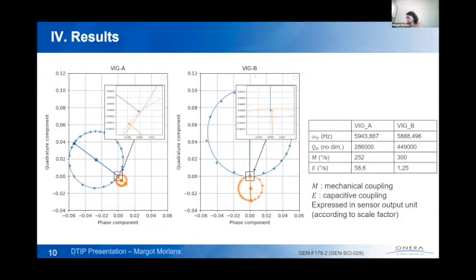We see some capacitive coupling, especially on the sense electrodes, which is particularly problematic since we know that the capacitive coupling has the same phase as the Coriolis coupling, which is, I remind you, our desired output. On the other hand, we see on the VIG B that capacitive coupling is much smaller than on the VIG A. In fact, the VIG B was tuned at factory level, which explains this result. Here in this table, we can see the numeric results. We obtain mechanical and capacitive couplings thanks to a scale factor, so they are expressed in sensor output units, which is degrees per second.